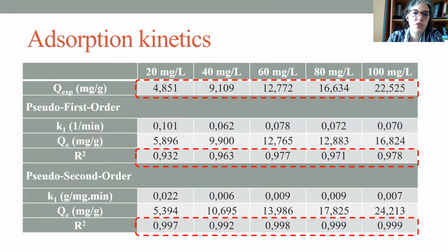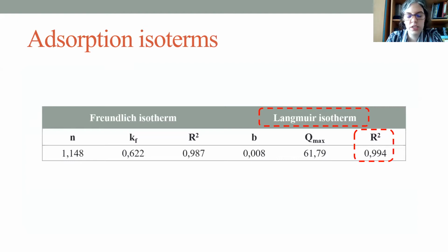Also, we calculated the adsorption kinetics. As I said before, two kinetic models were tested to explain the adsorption kinetics, and the rate constants were calculated. It was found that the pseudo second order model is in good agreement with the experimental data, and its correlation coefficient is higher than that of the pseudo first order. Also, to understand the adsorption process, it was analyzed with Langmuir and Freundlich isotherms, and the best correlation was obtained with the Langmuir isotherm.